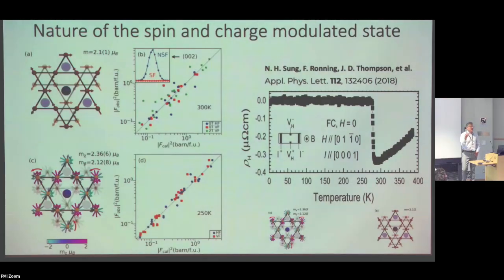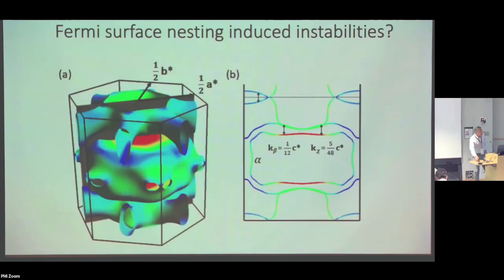And that is as you should expect, because it corresponds to having a ferromagnet with all possible different rotations or orientations at the moment. And so there's no longer a ferro character to the structure at all, and we lose that. So it's important to understand what eventually eliminates the effect that we are interested in. Also in this case, we're able to relate the incommensurate wave vector to nesting conditions on the Fermi surface. It's now a fairly complicated Fermi surface, but the large areas are separated from each other by wave vectors very close to those that we observe in the X-ray diffraction experiment.